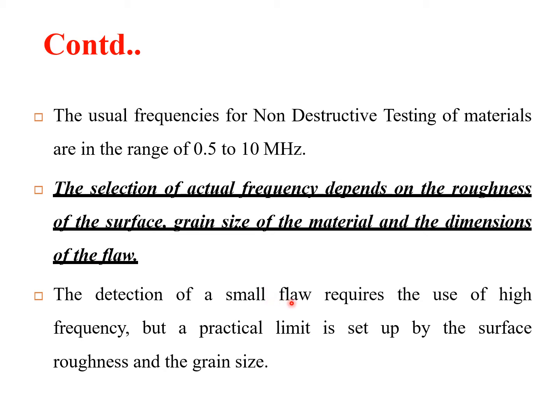The detection of a small flaw, that is, if you have a small discontinuity, requires the use of a higher frequency. That is, if the size of the flaw is small, you need to use higher frequencies, but actually there is a limit above which you cannot go. There's a practical limit that is set by the surface roughness and the grain size. So there are three factors upon which the frequency in this method is set.